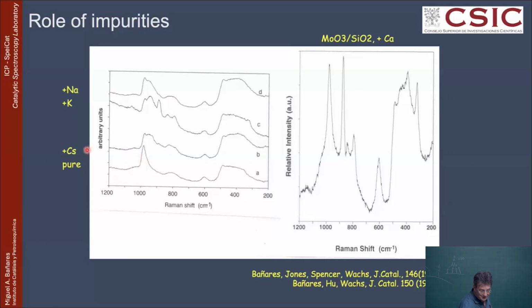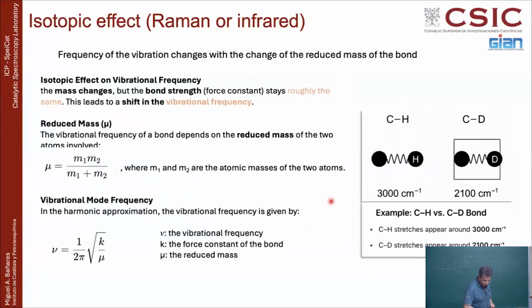Now, if there was some cesium, potassium, or sodium, you see something else. What do you think I see here? These new bands that are not apparent before. Crystals, exactly, alkali molybdate, cesium molybdate, potassium molybdate, sodium molybdate, or on the right, it was dramatic, it was calcium molybdate, very, very strong. These other bands that you see here, this is part of the silica. Silica has weak bands here. But these new things are from the sodium, potassium, cesium molybdate, and here you have calcium molybdate, it's quite sharp. And we are dealing with little loadings, and you can get already important information even about the role of impurities.